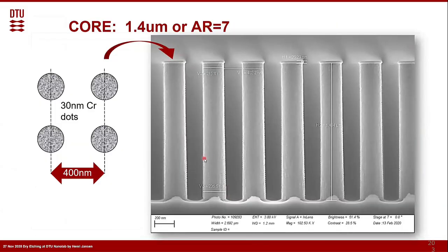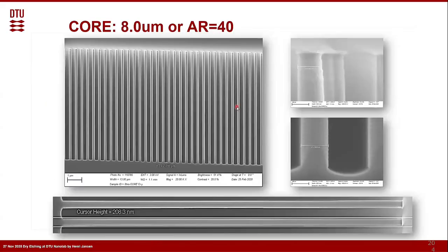For instance, if you look at it now, we have 30 nanometer chromium dots on top of silicon, and we etch for a certain number of cycles. You can see how much that could be, like 100 or so. And after a certain moment, it is 1.4 micrometers deep with an aspect ratio of 7. And we can just go deeper, 8 micrometers deep, aspect ratio 40. You see how nicely straight they are.